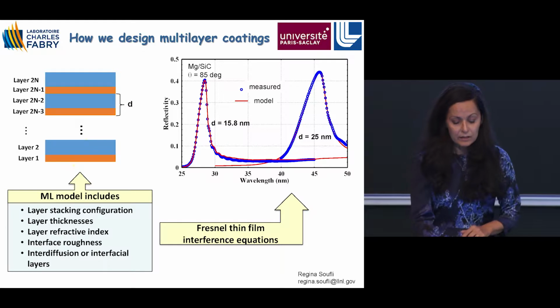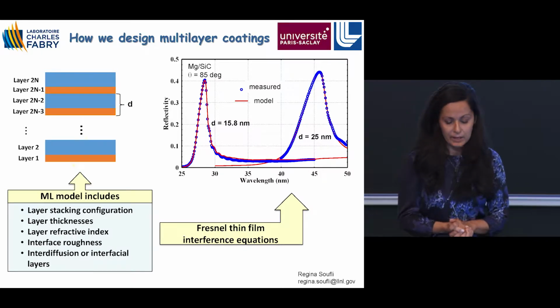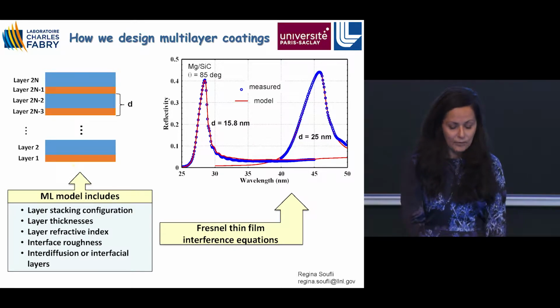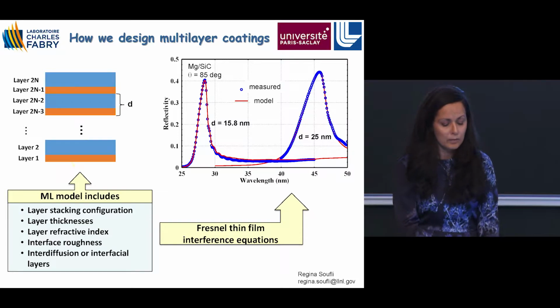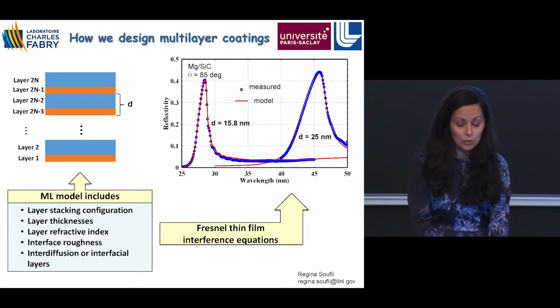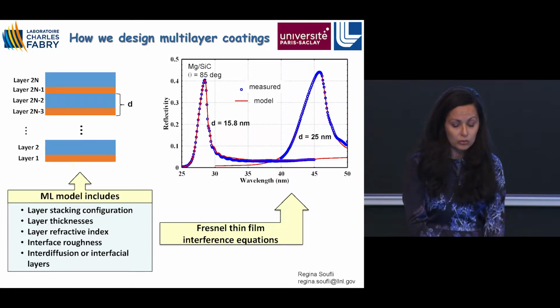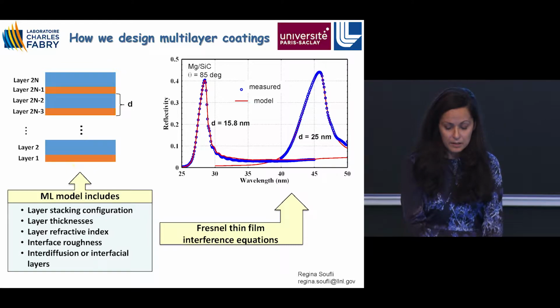So to the fundamentals, how do we design multilayer coatings? This is an example of a multilayer stack. Once again, you can have more than two materials. Here, to keep things simple, I'm showing just two materials. So you have a specific photon energy of operation. For example, you want your reflectivity to peak at about 28 nanometers, as we're showing here, or 46 nanometers for a different multilayer. These are two different coatings.